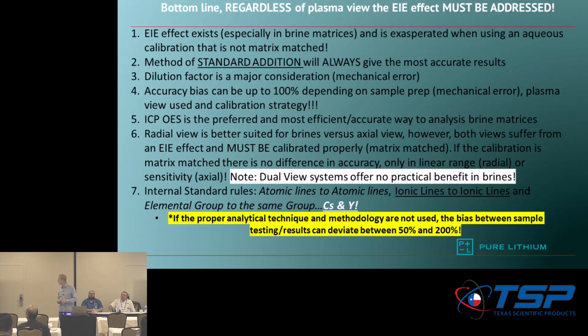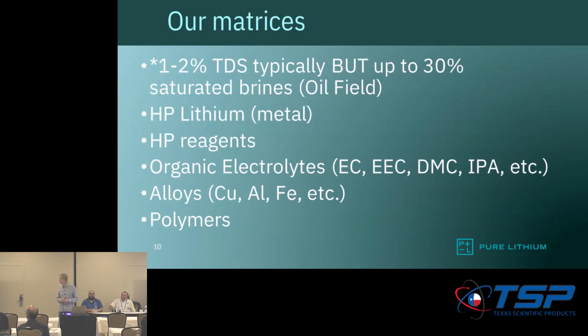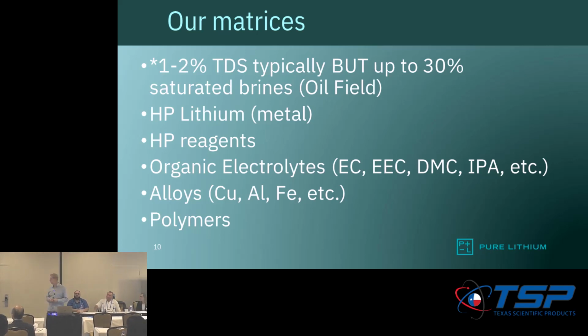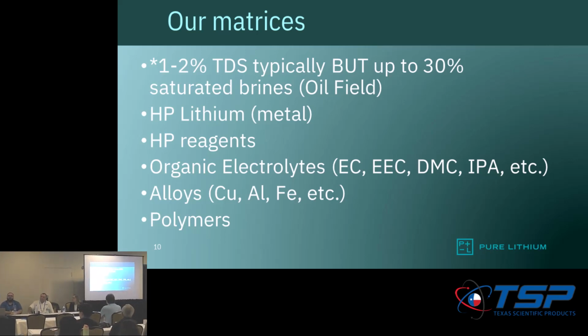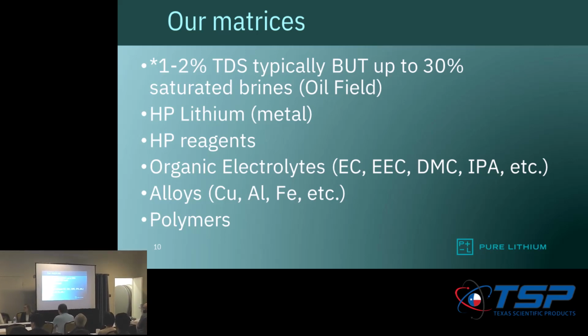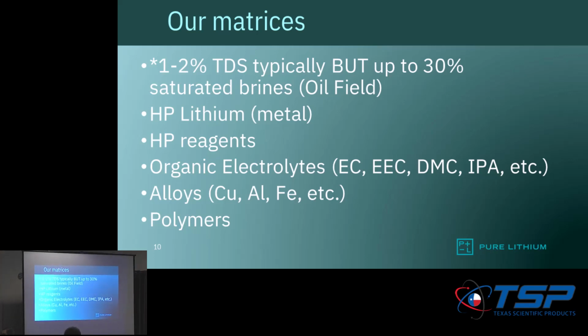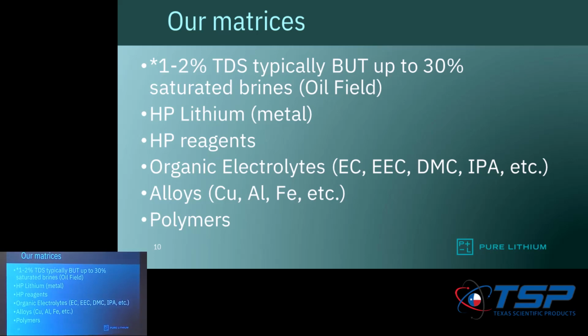All right, what do we run? We run typically, as I said before, oil field brines, usually 1 to 2%, but we can go up to 30%. We run high purity lithium metal. We run all the reagents that come in, the so-called high purity acids and DI waters and everything. A lot of organic electrolytes, which is what we use in the battery manufacturing. The substrates for the cathode, so they can be copper, aluminum, iron. And we even run our polymers. So we have a very, very unique selective polymer membrane. So just very quickly to tell you what we do.